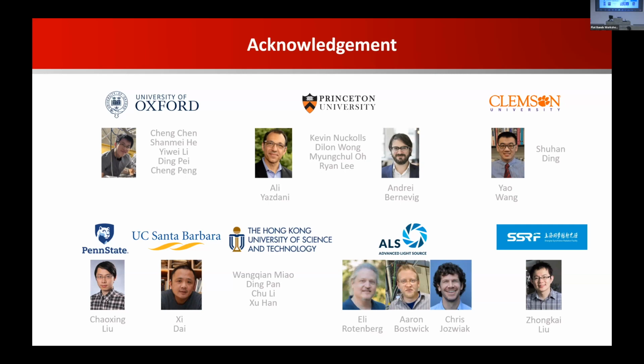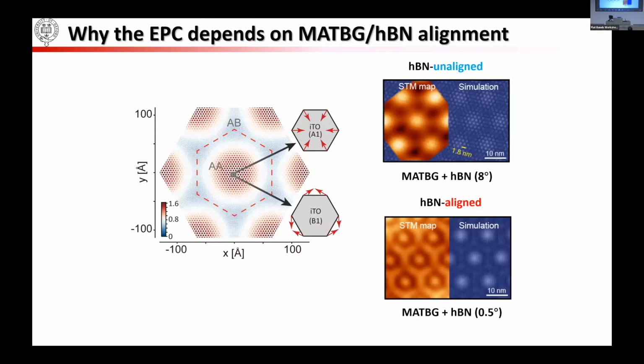The electron-phonon coupling can't disappear for the unaligned case, but it will be significantly reduced, to the point that we don't see the replica. Currently our understanding is this intuitive picture. According to our calculation, in the hBN unaligned sample the density of the electron accumulates at the AA site, from STM. For the aligned one, it's much more distributed. And for this ITO phonon, the distortion happens right at the AA point. So this is quite natural that for this case the electron-phonon coupling is stronger than this one.